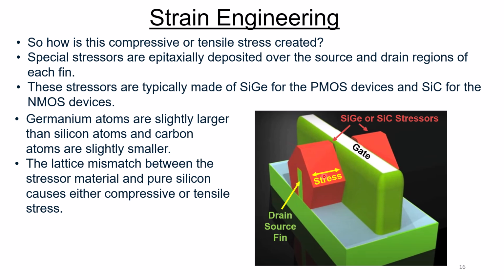The lattice mismatch between the stressor material and pure silicon causes either the compressive or the tensile stress that you're trying to achieve. And once again, let's look at this drawing over here. So in this case, the fin is kind of hard to see. It's underneath the stressor material here. And you're applying a stressor to the left and right side of the fin here. And it's either, again, silicon germanium or silicon carbide, depending on whether you want to create compressive stress or tensile stress.